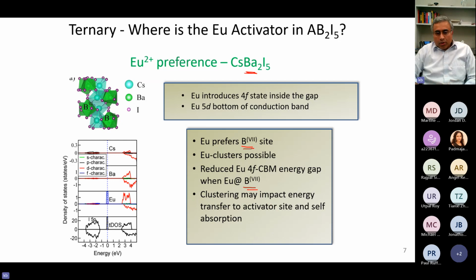What we found through our work is that europium prefers the 7 site. Now we found that the europium prefers the barium 7 site, sorry, not the 8 site. Why? Because there are chemical reasons. Europium wants to be most comfortable, right? In the lattice, it finds this location to be most comfortable, and therefore it prefers that site.